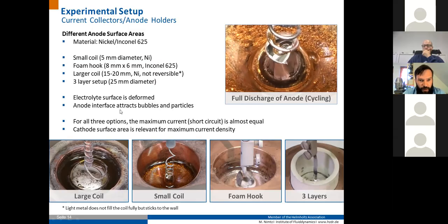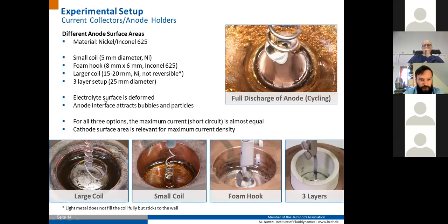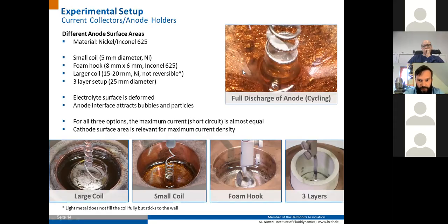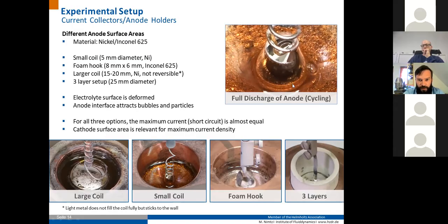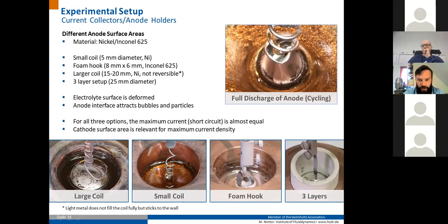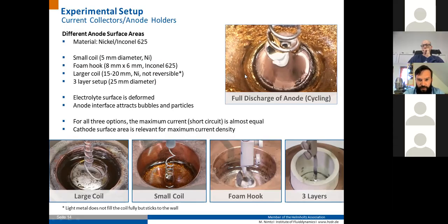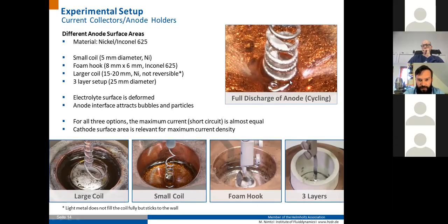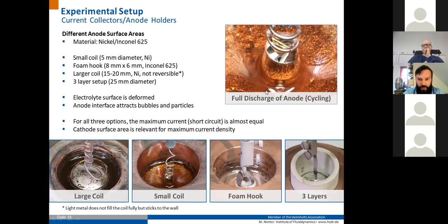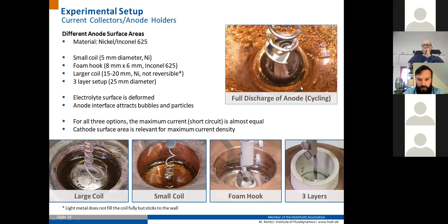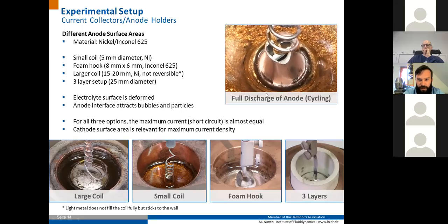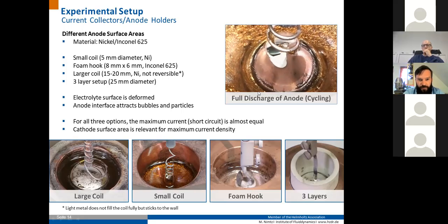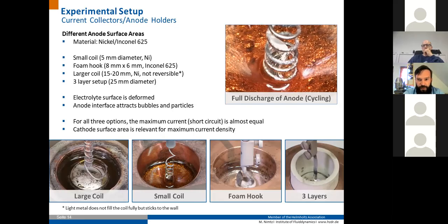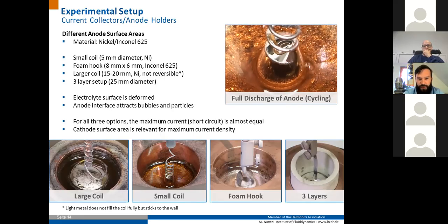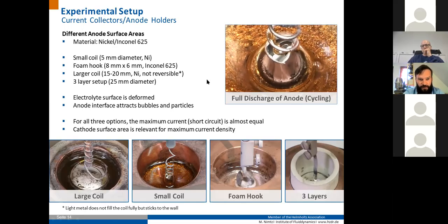One thing you will always see is that the electrolyte surface is deformed, as you can see here. And also the surface of the anode droplet here is deformed due to the different densities, which makes it quite difficult to get an idea about the real surface area in contact with the electrolyte.